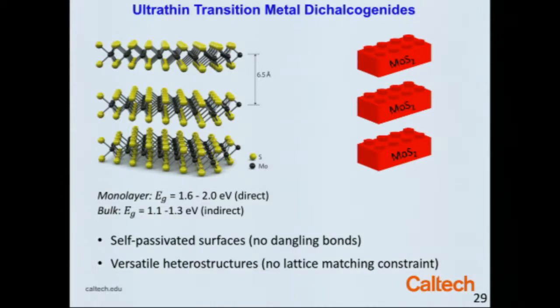So if we can make large crystals or functionalized edges, we can make materials with very interesting properties. It turns out that in their monolayer form, they form direct bandgap semiconductors—I'll show you in a minute—with very, very high luminescence efficiency. If you make them multi-layer, they're indirect bandgap semiconductors, but actually in the right bandgap range for use in photovoltaics. So these are quite interesting.